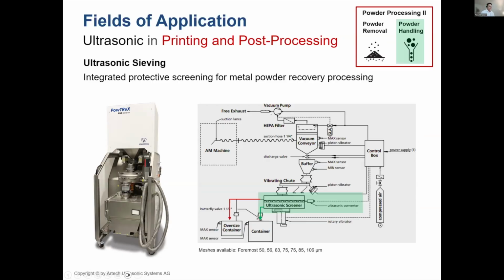So as you can see from this figure, the powder goes from the AM machine back to the recovery process, and over a buffer, and the vibrating chute will then dose it into an ultrasonic screen. And then the ultrasonic screen makes sure that the oversized particles go as fast as possible, as precisely as possible into the oversized container, and vice versa, the good powder into the good container.